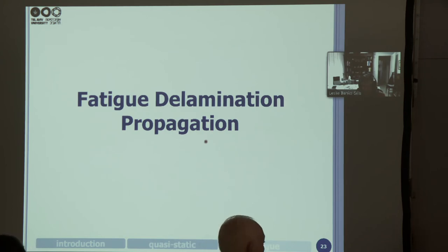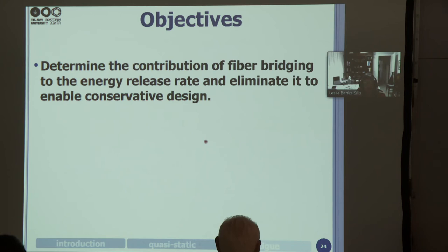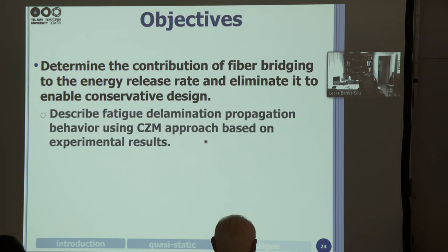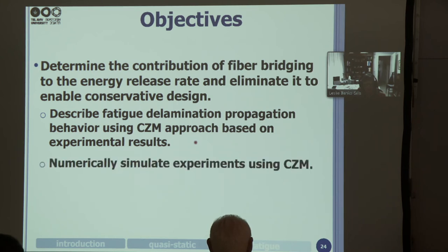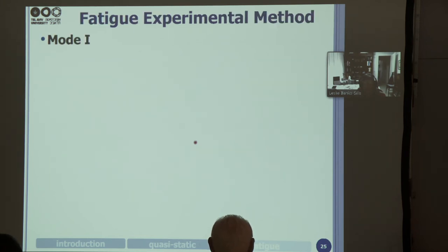And I've lost the time, but I think we have enough time. In this case, again, we want to determine the contribution of fiber bridging to the energy release rate and eliminate it to enable conservative design for structures. So we're going to describe the fatigue delamination propagation behavior using a cohesive zone model approach based on the experimental results and based on our experience with the quasi-static testing, except there's going to be more damage here. So we numerically simulate the experiments using the cohesive zone model.